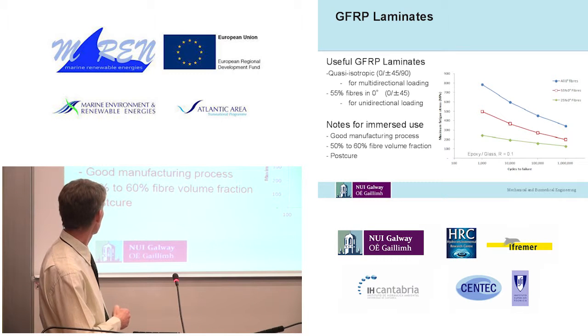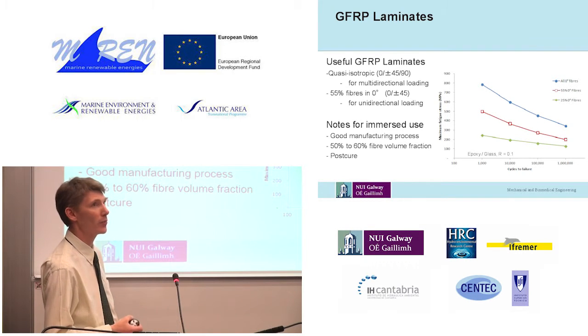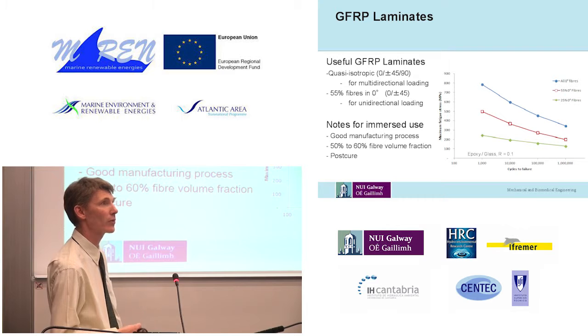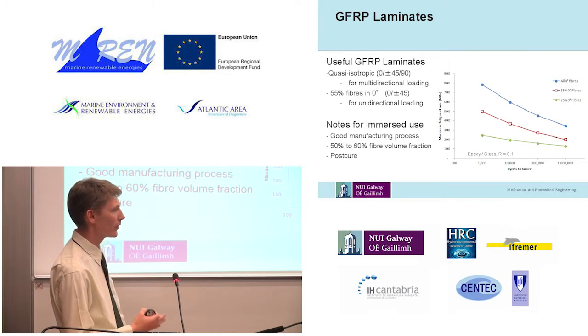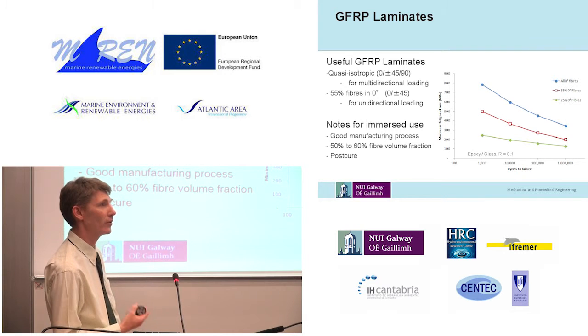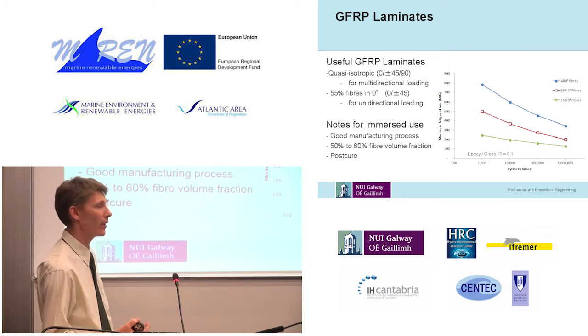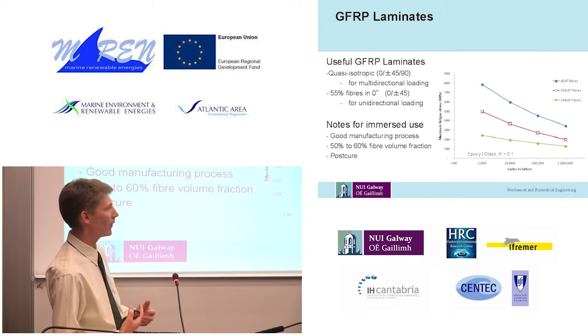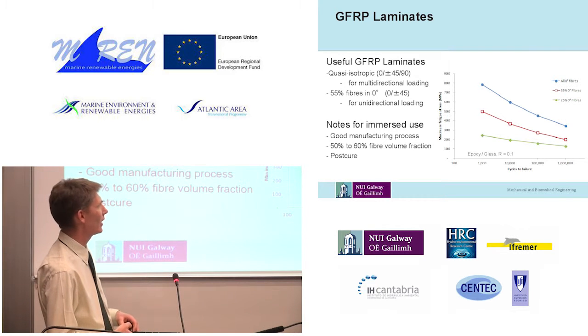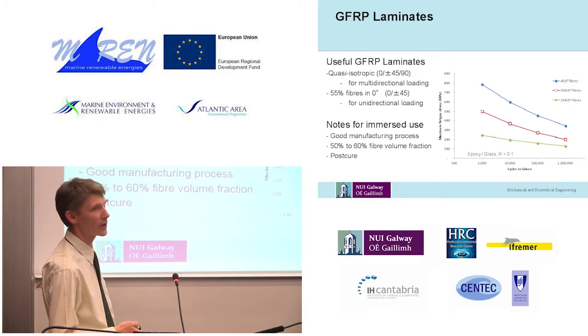And the final thing I'd mention here is that it's a good idea to post-cure the laminate, and that's a process where after the material has been set for maybe 24 hours, you heat it up to maybe 80 degrees centigrade, and that allows the final cure to take place, and it gets the properties in the right place for you.